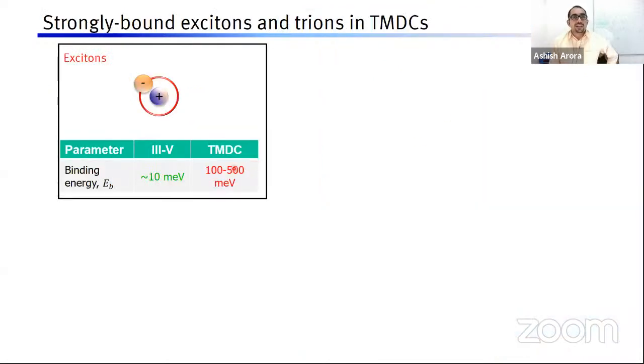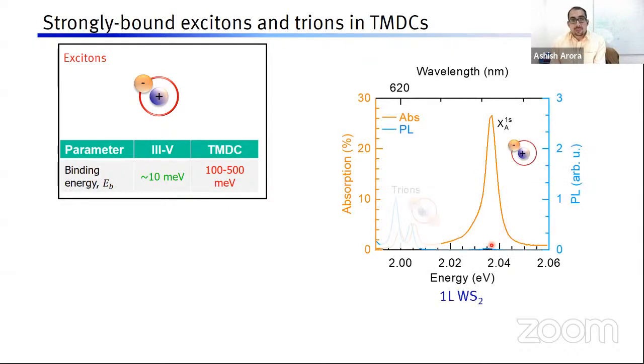The point is that in these TMDCs, or transition metal dichalcogenides, the binding energy of excitons is very large. It's an order of magnitude larger compared to the III-V semiconductors. And the excitons appear as a strong resonance in the absorption spectrum. For example, this is a monolayer tungsten disulfide layer. And here this orange is the absorption spectrum of an exciton.